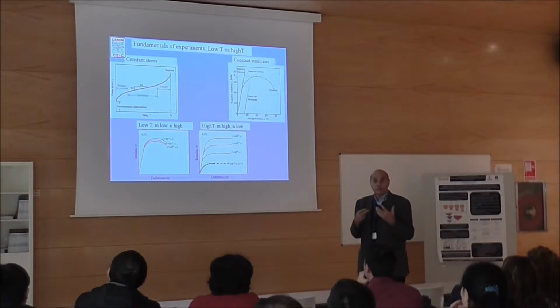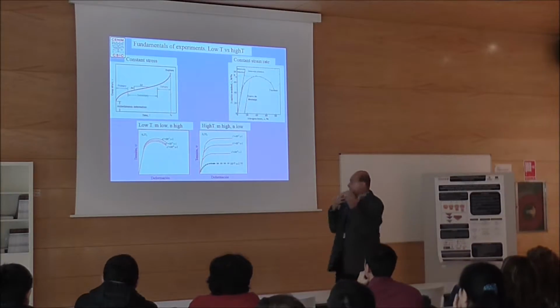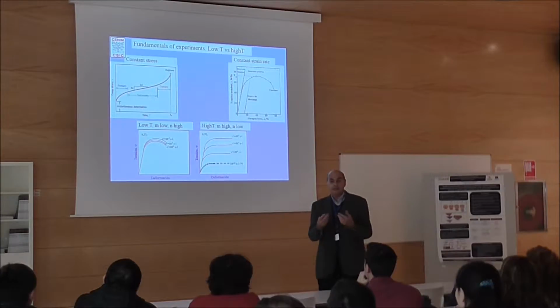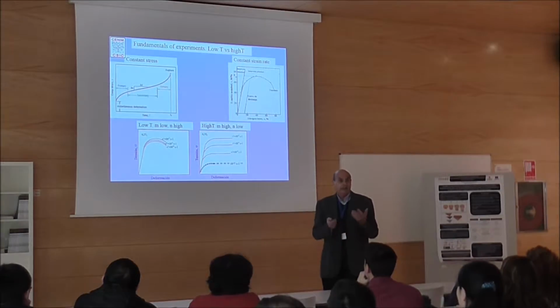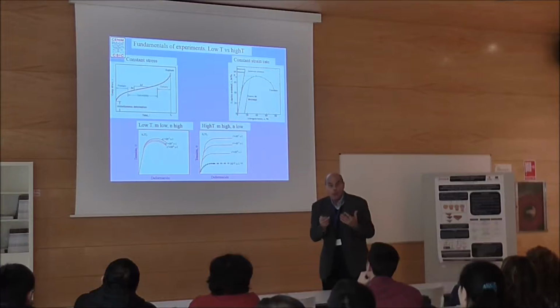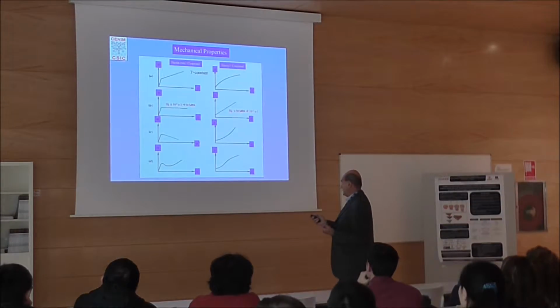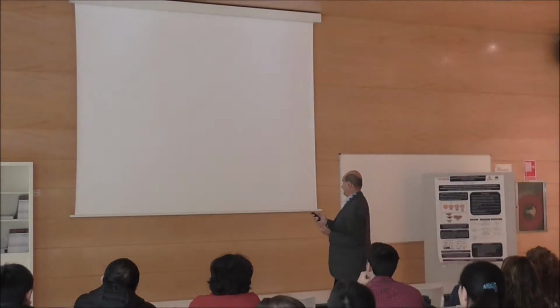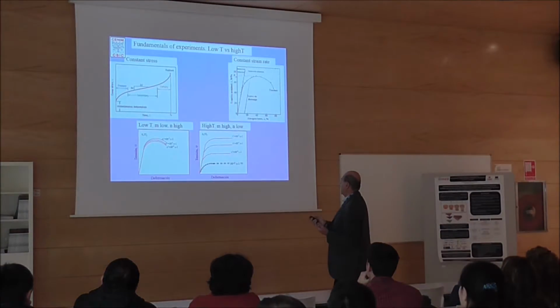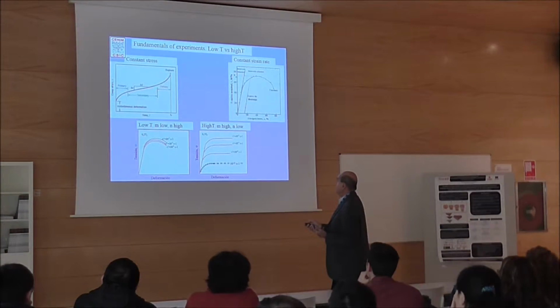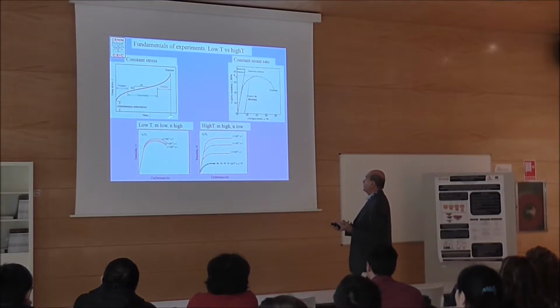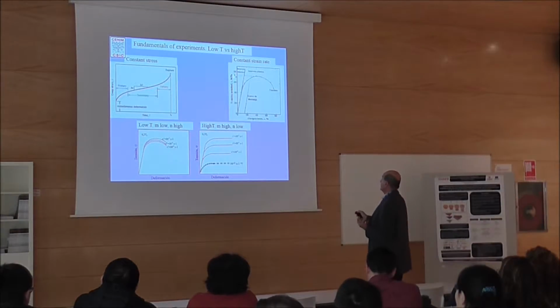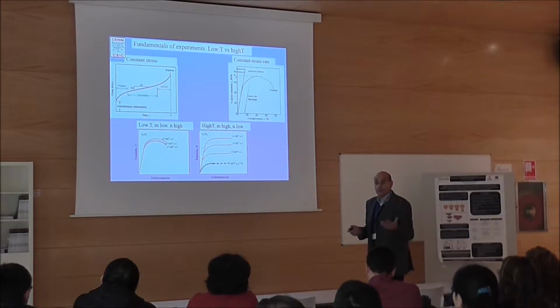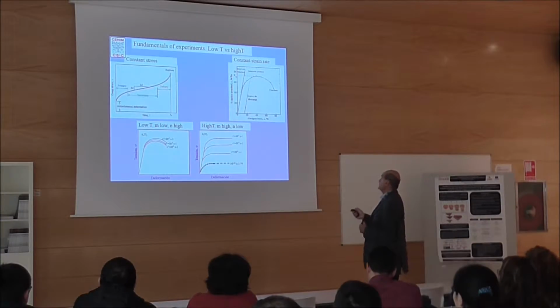So what we do is to make creep tests. But this is the other fundamental thing on the experimental side. You don't need to have a creep machine. The creep machine will be used only for lower strain rates. This is a creep curve, opposite or in contrast to the usual one that we have in the MTS or the instrumented machine. We can obtain creep data from both this and this.